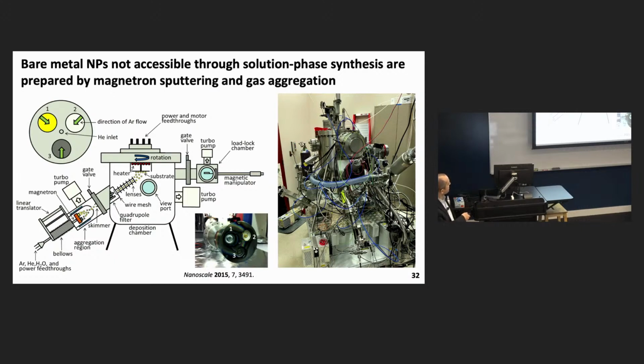One thing that's unique about this device is that instead of one single target, you actually have 3, and you can control the power applied to each of these sputtering targets independently, which means, at least in theory, you can control the mole fraction of each metal that you incorporate into the nanoparticles. So because we generate a distribution of charges, cations, anions, and neutrals, we normally work with the neutrals, so those are extracted. We can use a mass filter to select a particular size range we're interested in, and then again, we can focus and deposit these materials at controlled energy. And this gives you a way basically to make a model catalyst material for oxygen reduction.